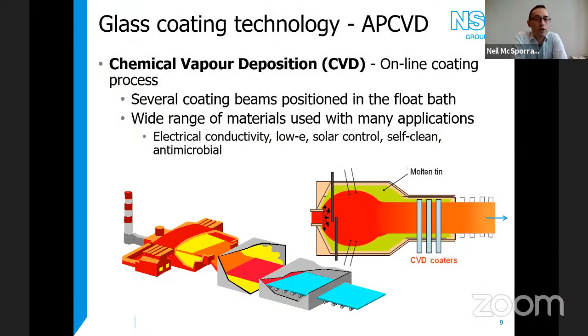So chemical vapor deposition is probably our strongest technology, and with that, we actually deposit our coatings during the glass manufacturing process. Now, the challenge of that is that we're operating within the float bath, and as I mentioned, you're coating on a continuous stream of glass, and you're putting down complicated multi-layer coating stacks on a continuous stream of glass at a very high temperature, typically around 600 to 700 Celsius. So as you can imagine, a high degree of monitoring and controllability is needed during the process.